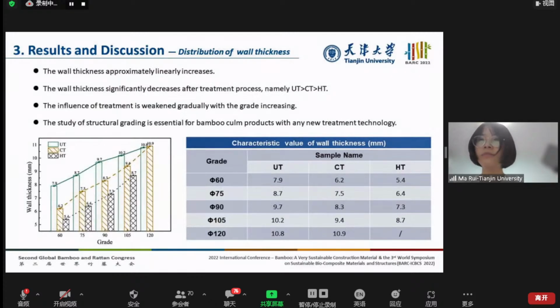Comparing the characteristic wall thickness value of each grade, it can be seen that the wall thickness increases approximately linearly with the grade growing, which means that the larger the external diameter, the thicker the wall. Wall thickness significantly decreases after treatment process in the same grade. The wall thickness of UT is larger than that of CT and HT. The influence of treatment is weakened gradually with the grade increasing. Results prove that the study of structural grading is essential for moso bamboo culm products with any new treatment technology.